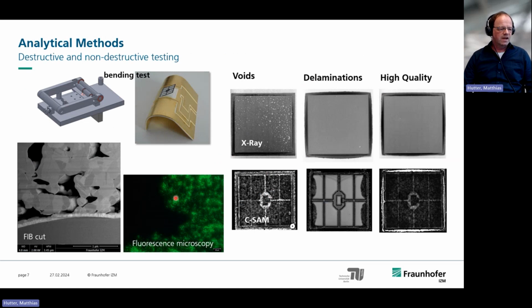In order to qualify such joints, we have, of course, destructive methods, but it's not so simple because of the large area to do shear testing. One of the first things you can do is just use a bending test, and if it looks like this, the quality was not so good. Of course, we can use FIB cuts in order to see the interfaces and also the porosity. And very important, besides the X-ray, where you can see defects like voids, is acoustic microscopy, where you can see two-dimensional defects, like for example delaminations, as you can see here, which could not be seen in an X-ray photograph itself. So these two look the same, but the quality is really different. This is a high quality, and this is very poor quality.